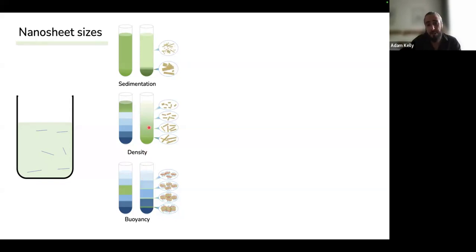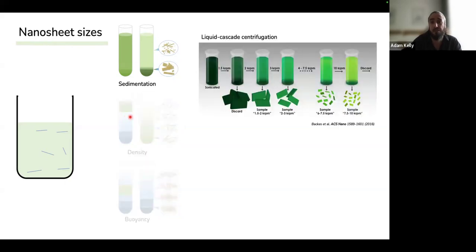Now, as you can imagine, these two methods, using density and buoyancy, are quite difficult to do, because if you want to extract your nanosheets out of this layer, it's actually quite diffuse. These layers tend to be between the interfaces. So the easiest way to do this is just by using sedimentation. Now, this is a method known as liquid cascade centrifugation.